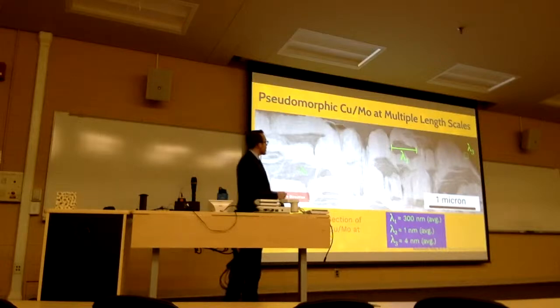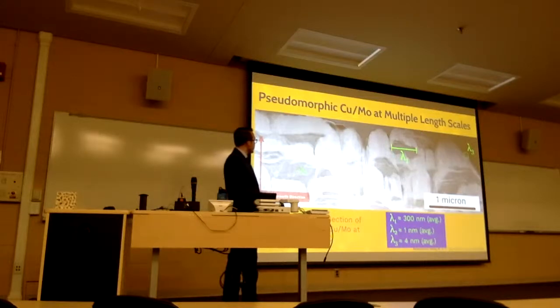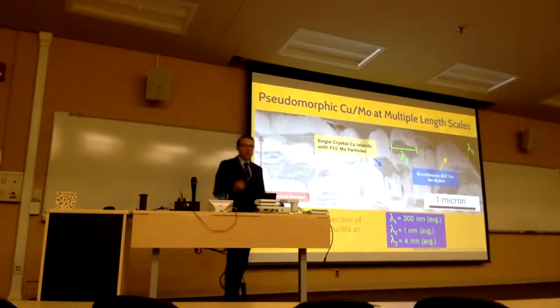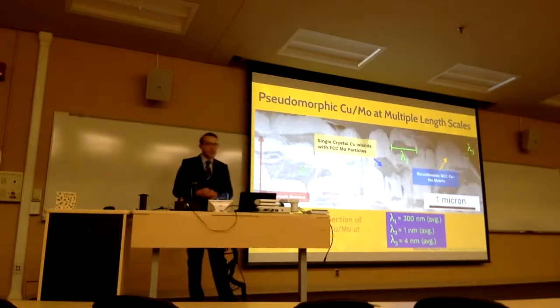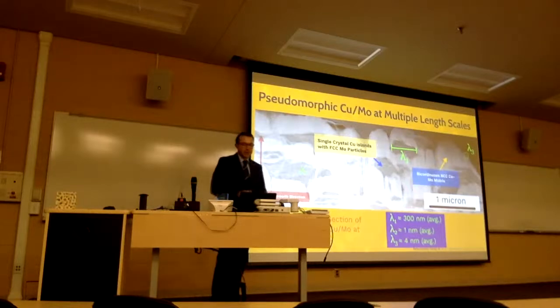The first length scale, as you can hopefully see, are these dark regions scattered throughout a brighter matrix in the sample. And what these are actually single crystal copper islands, and they contain a little bit of FCC Mo particles, which I'll describe to you in just a second. That brighter region you see in the sample is actually a bicontinuous morphology that's surrounding those copper islands. So that's lambda 1. What about lambda 2?